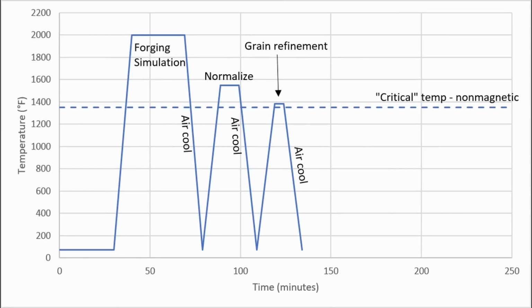Another thing I do want to talk about is heat treating with a forge. I do have a separate video on how to heat treat with a forge, but I do a very simple method where you can heat to non-magnetic and no hotter and then quench straight away. So with nothing but a magnet, you know when the steel is ready to quench.